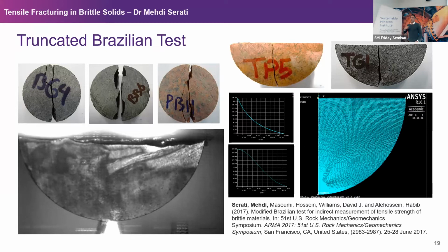It suggests if you can't fully comply with the standard recommendation for Brazilian tests because of the nature of the rock you are dealing with, another alternative might be, you cut it in half, you load it up this way. Of course you need to have the geometry measured, you need to have this contact angle, and we prepared some specific spacer. You put it in that equation and it gives you an estimation of what would have been the induced tensile stress responsible for this tensile crack.